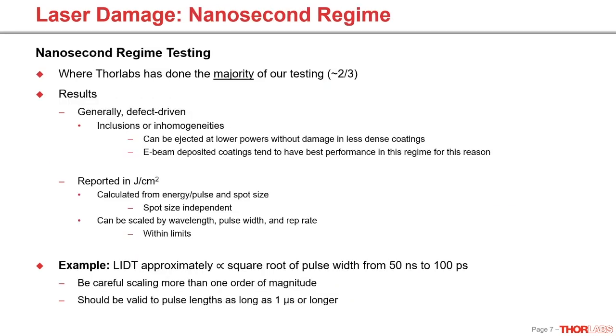So yes, we've done the majority of our testing, approximately two-thirds of the parts that I'm aware of, in the nanosecond regime. And again, this is due to a focus of customer demand in that area. As far as the results of that, in general, the nanosecond regime damage threshold is driven by defects. And these are inclusions or inhomogeneities either in the coating or in the substrate itself. And these are caused by either inherent remnants in the substrate, because obviously any substrate you get is going to have some remnants from the crucible that it was grown in, or some remnants from the optical polish that was used to prepare it. Whereas coating inhomogeneities are typically driven by cleanliness of chamber, purity of materials, depth of vacuum, all that stuff.